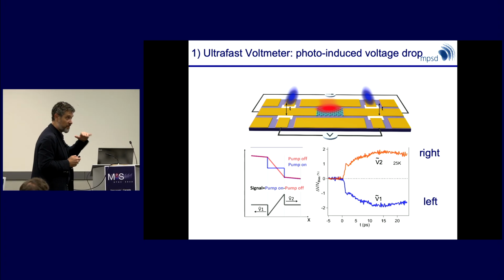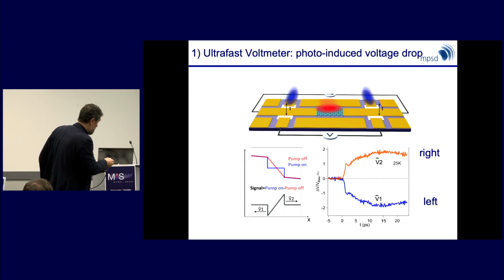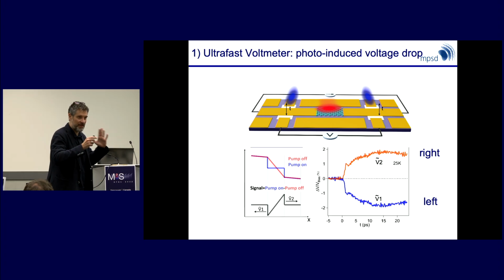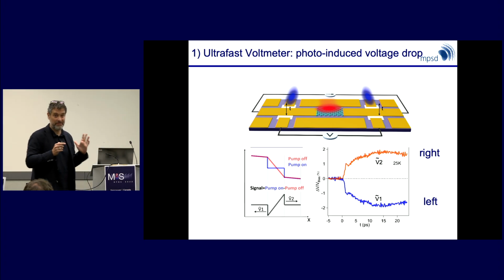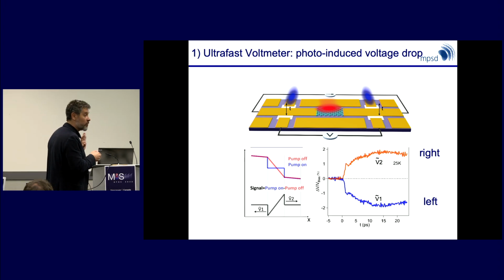There is a transition from a metallic state to either a better metal or a superconductor. You know, this is difficult. There's now the problem of terahertz contact resistances and kinetic inductances, and this thing is going to ring like a bell. So doing quantitative measurements at these time scales is not something we've mastered. But qualitatively, we observe the right thing. This is an ultra-fast voltmeter, where I'm doing the transition, and now I see the change.